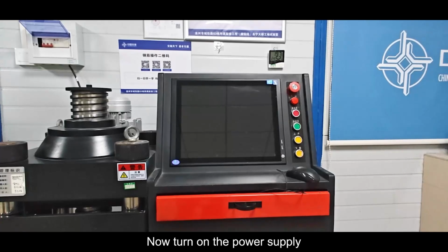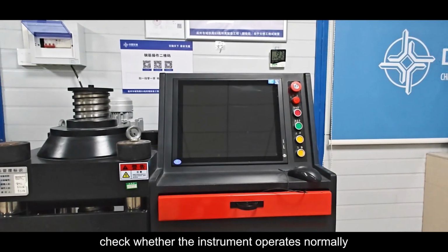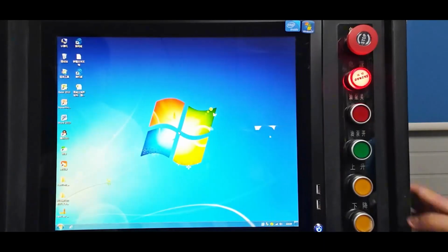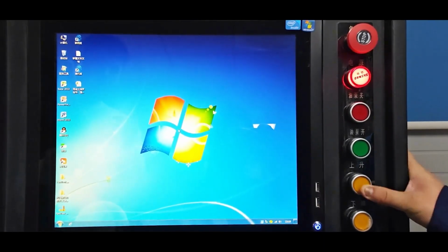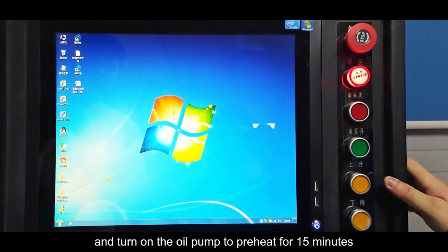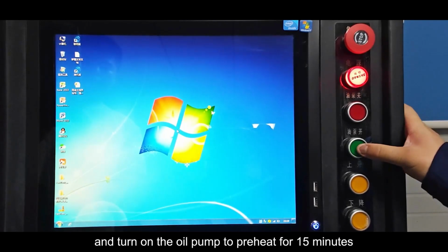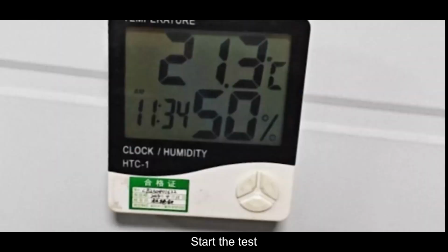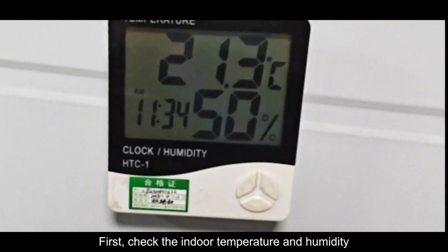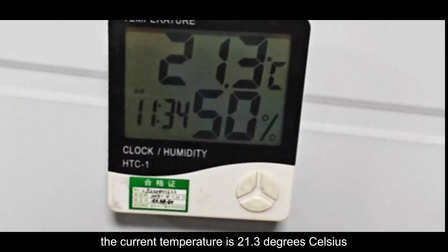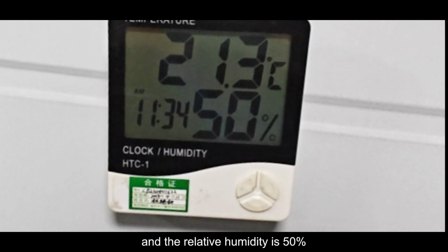Now turn on the power supply, check whether the instrument operates normally, and turn on the oil pump to preheat for 15 minutes. Start the test. First, check the indoor temperature and humidity. The current temperature is 21.3 degrees Celsius and the relative humidity is 50%.